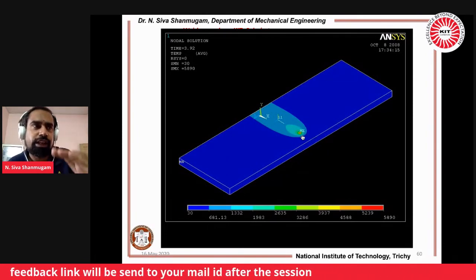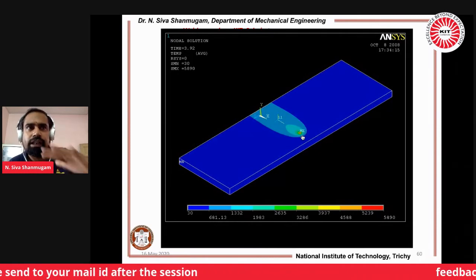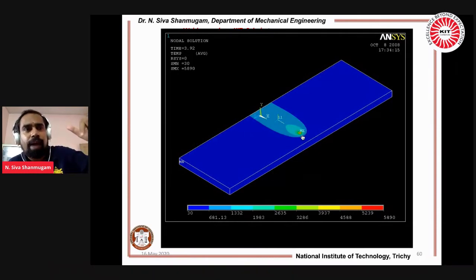The XY energy distribution on the top surface is minimal compared to the energy distribution, which is very high along the thickness direction. That's why, if you compare, the preheating zone is very minimal, and in the post-heating you see a very wide temperature region. It is something around 600 to 1332 Kelvin.